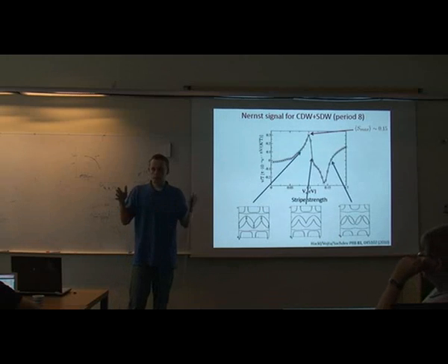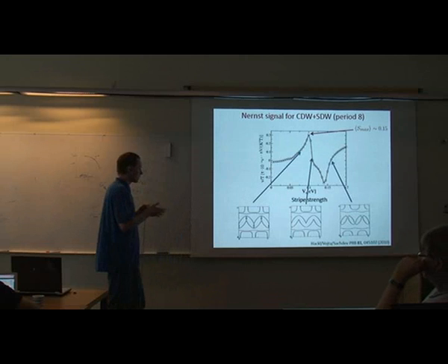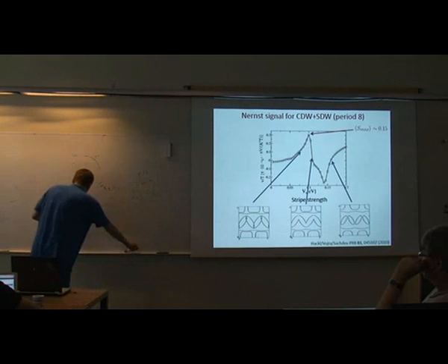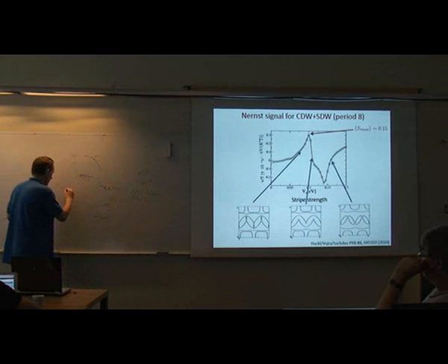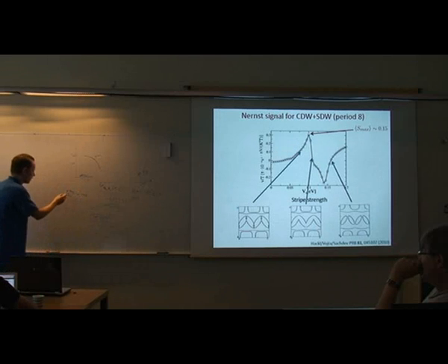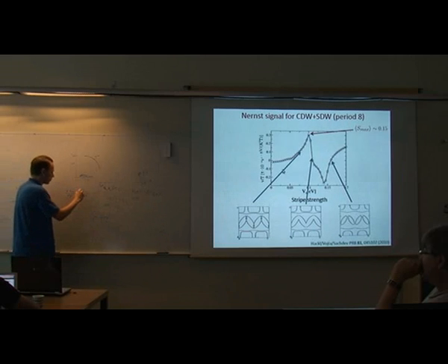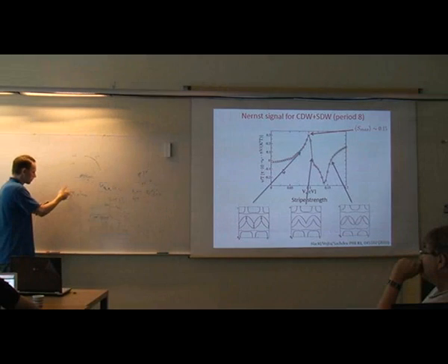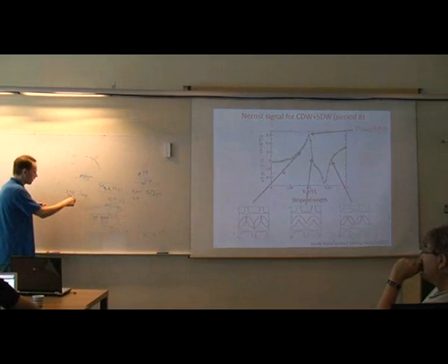Once you move to a Van Hove singularity, you essentially get some singularity in the signal. There's the fundamental function based on the fact that you can rewrite this derivative. All the thermoelectrical quantities are essentially derivatives of the electrical quantities with respect to the position of the Fermi surface, maybe times some temperature. And due to Van Hove singularities, this quantity is highly singular.